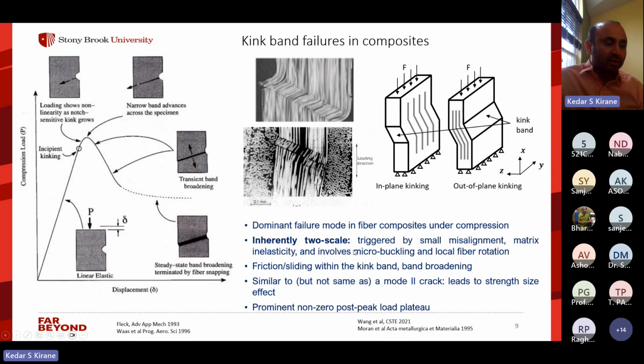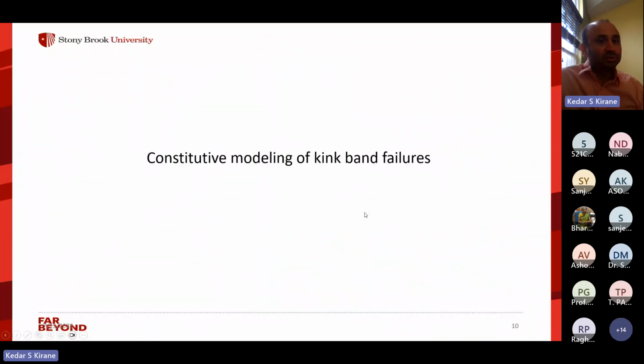The localization is there. There is friction and sliding within the kink band after it forms. And overall, its behavior is actually like a shear crack. So it is similar to, but not the same as a mode 2 crack. And so this also is a quasi-brittle mode of failure, and it leads to a size effect on strength. So to be able to predict this in models, the model needs to account for all these in a meaningful way.